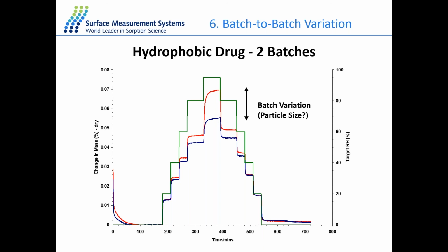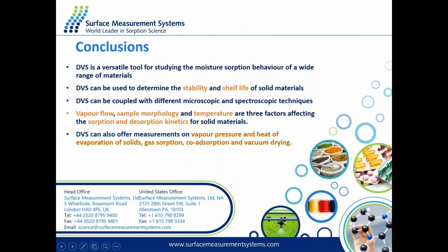Normally, if the moisture sorption is above 1% mass change, we can say it's a bulk sorption dominating mechanism. And if it's below 1% mass change, it's basically surface sorption, where most of the water molecules just condense on the surface with very low uptake. And I think that's probably all for my applications.